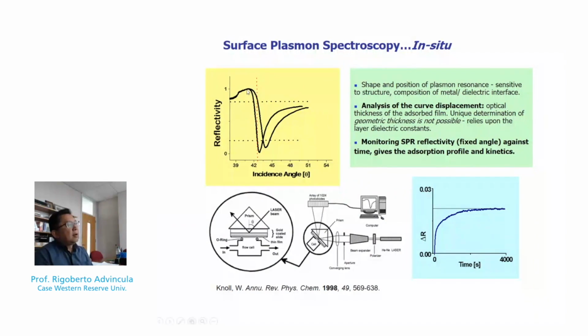One of the things that you can rely on is the shift that occurs as you add a dielectric medium on top of gold. And this shift, as shown here, goes to higher angles. Now, if you observe the intensity at a fixed angle, you can draw this red line. That means that the intensity or reflectivity is different from the original gold surface all the way to the added organic film. And that means as you are increasing the thickness or the dielectric shift on that organic film sitting on top of gold, and then you simply monitor that as a function of time, let's say in a flow cell condition, that actually becomes a kinetic experiment.